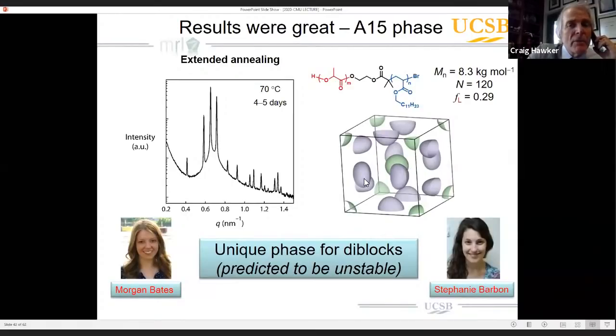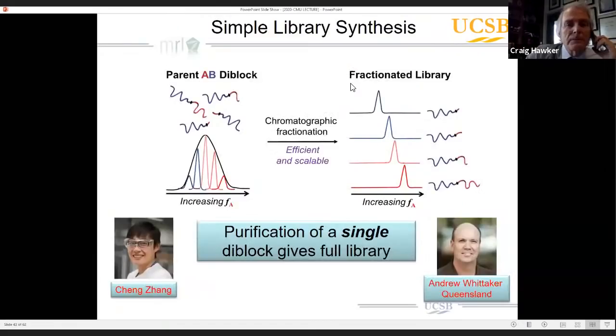It's a spherical phase with a very large unit cell. And even I, who do not know that much about SAXS patterns, will recognize how pretty this SAXS pattern is for this A15 phase of this polylactide, polydodecyl acrylate diblock copolymer. The other interesting feature that I found from Morgan and Steph's work was that these materials were stable. You can extend and anneal these for long periods of time. And again, unlike the predictions, the A15 phase proved to be stable.